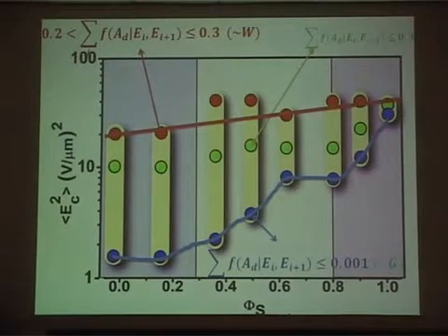If I took my threshold area to be very small, if I said I'm bothered only about where the first failure events happen, then EC square, which is the stress, the critical stress, increases dramatically with my volume fraction. So it's a very sharp increase. This is another measure of actually the error bar in some way. You can see this again. So it goes up very dramatically.